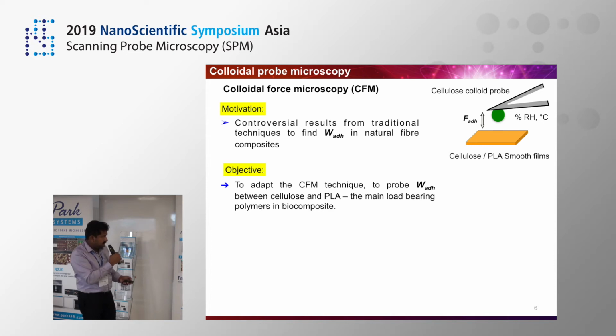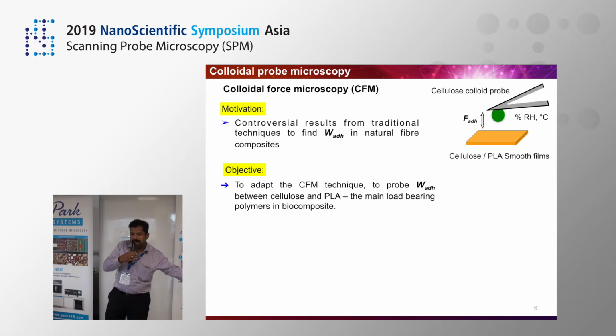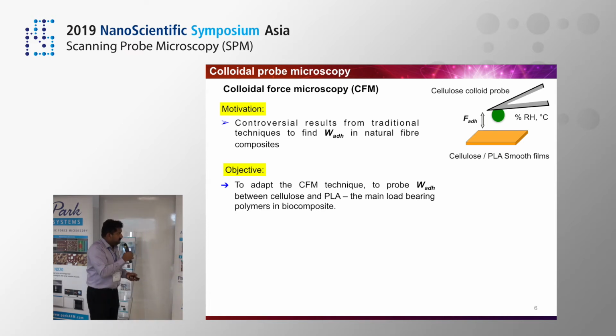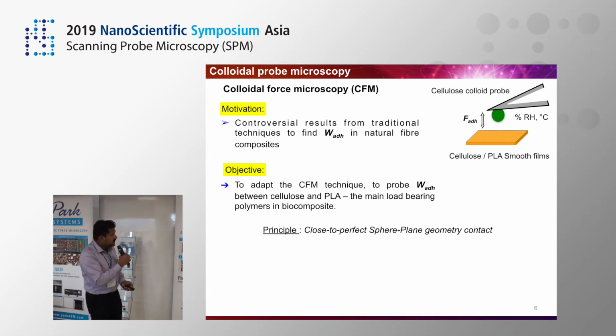So our major objective to choose this method, especially for these natural fibers, was that there are controversial results in the literature concerning the work of adhesion measurements in composites, because in one lab they use one type of fiber, in another lab they have another type of fiber. The values are very scattered. So here our objective is to use this colloidal probe technique to measure the work of adhesion between cellulose and PLA, which are the main load-bearing polymers in the biocomposite material.